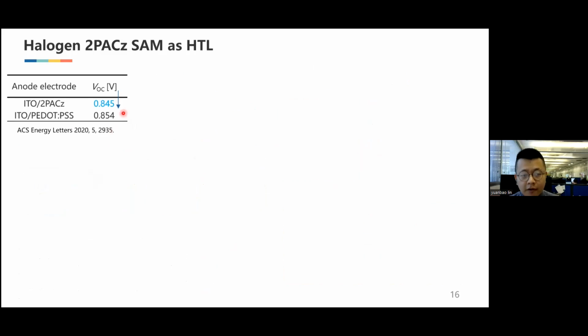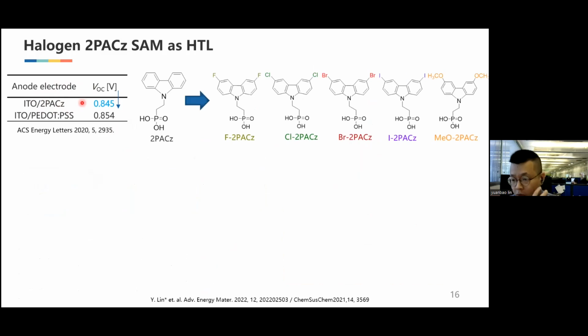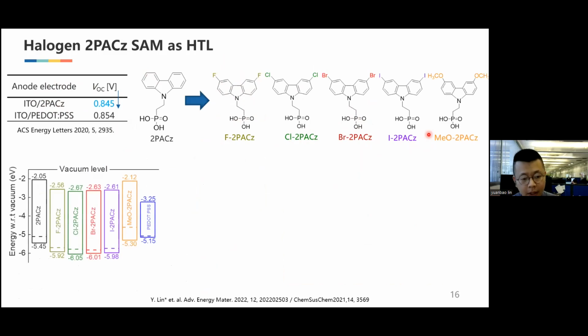But we also notice the VOC of the ITO/2PACz SAM-based device is slightly lower than the PSS. So we tried to synthesize new ones with different functional groups like fluorine, bromide, and MeO. With different groups, the work function and energy level change a lot. For example, for the bromide 2PACz, the work function can go to 5.8, but for the MeO-2PACz, the work function is reduced to 4.6. So we chose these 3 materials to test in the OPV.